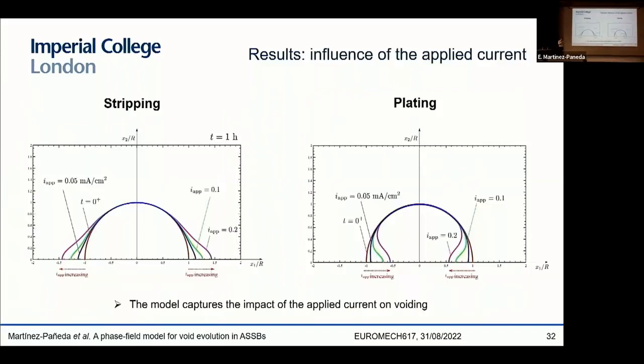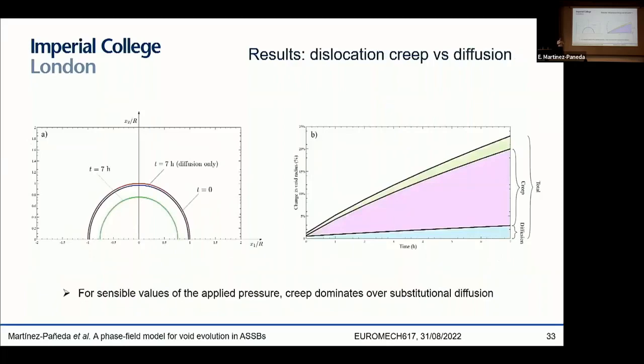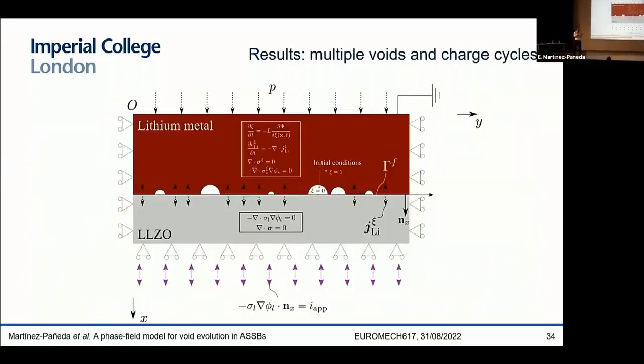And of course, then we can change parameters in the model and try to see if we get the qualitative behavior that we expect to see from the experiments. For example, we can change the applied current, and as you would expect from the experiments, the higher the applied current, the higher the rate at which the shape of the morphology of the void changes for both stripping and plating. You can also use the model to try to understand the interplay between creep and diffusion and see which one has a higher contribution relative to the other. And this is something that has been discussed widely in the experiments. And of course, you can use the model to capture any kind of realistic scenario, right? I was showing results for a simple boundary value problem, but you can capture behavior of multiple voids over multiple charge and discharge cycles, and any arbitrary, I would say, initial distribution of voids or pressure or charging conditions.